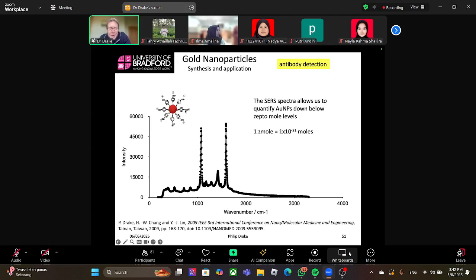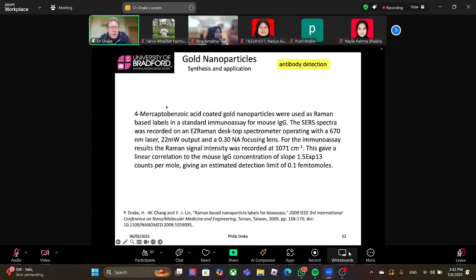So using mercaptobenzoic acid labeled nanoparticles, we can make SERS systems which can detect femtomole levels. So we can now count nanoparticles at a very low level, 1 times 10 to the minus 21 moles. And then we can use these as labels. When we shine a Raman laser on the system, we get these 2 peaks appearing. We can detect these nanoparticles very easily. So we can label antibodies using these nanoparticles, and that gives you ultra-sensitive detection systems.